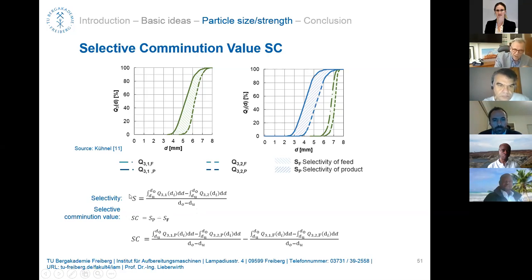Essentially we defined the selectivity as the area between the two curves, and the selective comminution value is then the difference between the two curves of the feed and of the product. If you have a mixture of two materials like quartz and limestone, you might have slightly different curves of the feed materials already. So there could be these two curves here, and we see the selectivity between the two already as a starting point. And then we see how this selectivity might have changed in the comminution process.